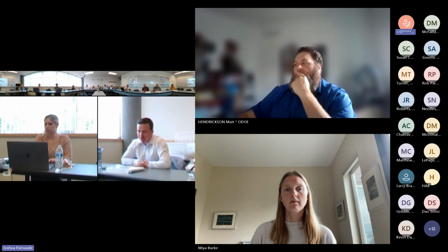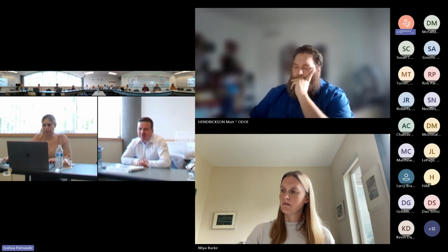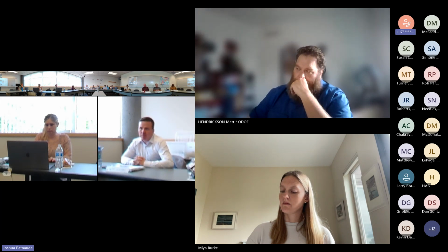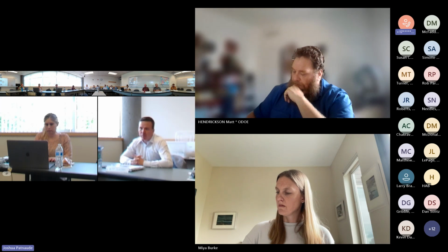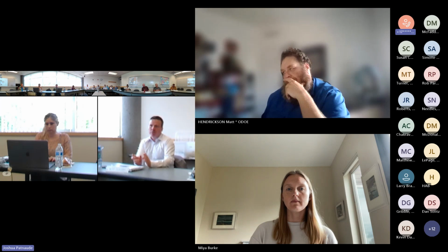Yeah, so this is where definitions really start to cross over with one another. First, saltstone is a specific formulation range approved for use at the Savannah River Site. It started out as a mixture of fly ash, blast furnace slag, and Portland cement, and it is now cement-free saltstone. Christine Langton is the scientist down there who's done decades of great work, where they've moved away from cement because of the cost and ensuring supplies of it. So saltstone is a specific formulation that Savannah River uses to immobilize their low-level salt waste into the saltstone disposal units. Its main components are slag and fly ash.